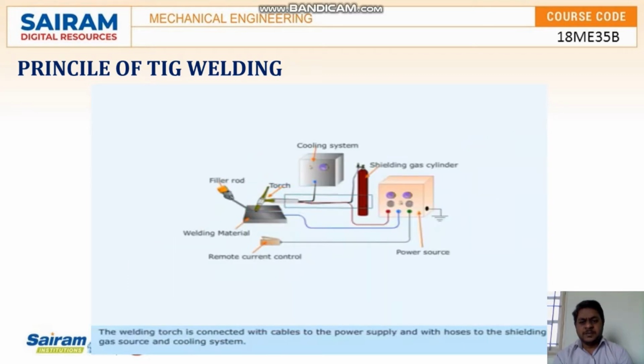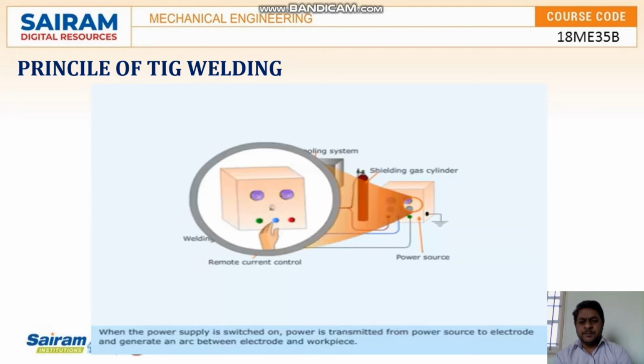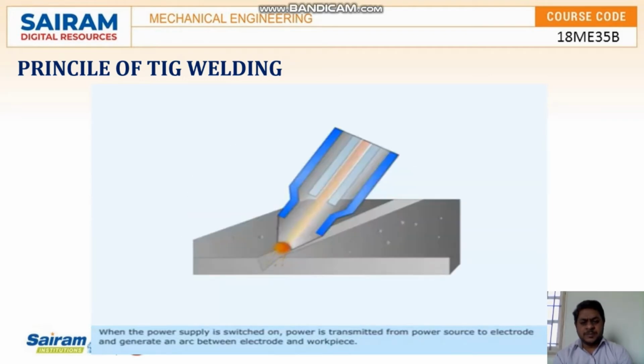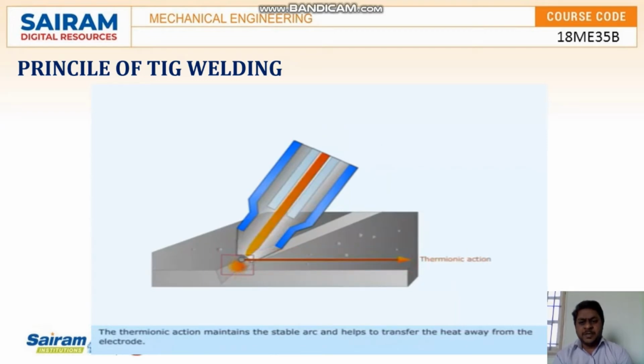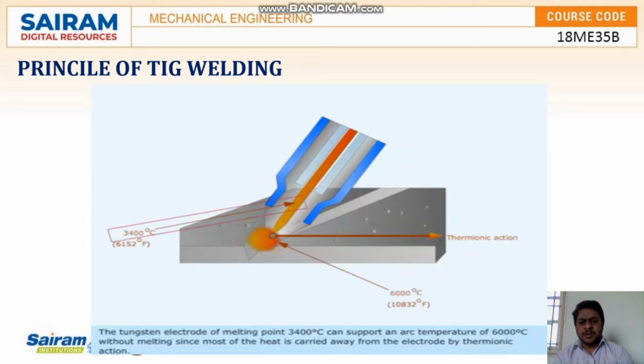The welding torch is connected with cables to the power supply and with hoses to the shielding gas source and cooling system. When the power supply is switched on, power is transmitted from the power source to the electrode and generates an arc between the electrode and workpiece. The thermionic action maintains a stable arc and helps to transfer the heat away from the electrode. The tungsten electrode of melting point 3400 degrees centigrade can support an arc temperature of 6000 degrees centigrade without melting, since most of the heat is carried away from the electrode by thermionic action.